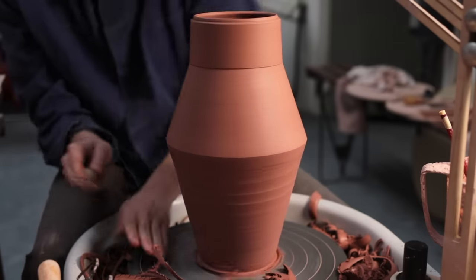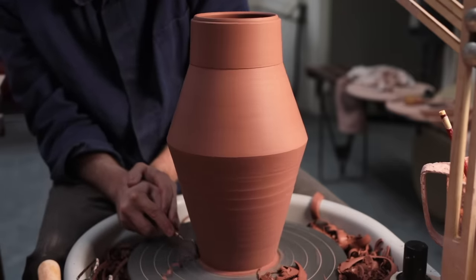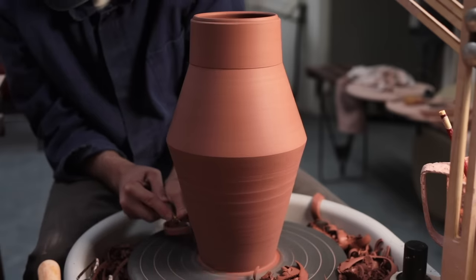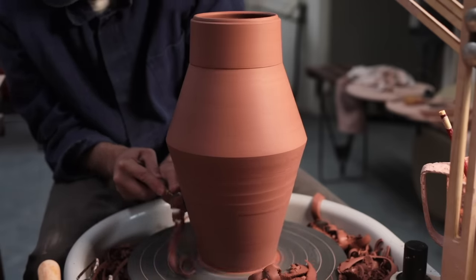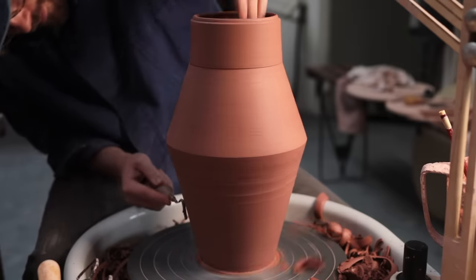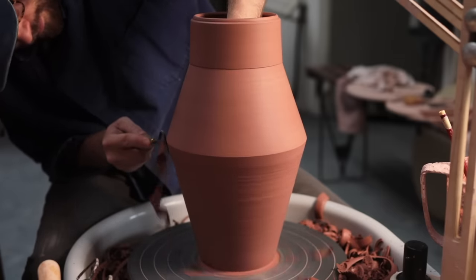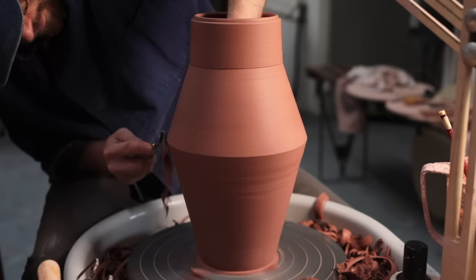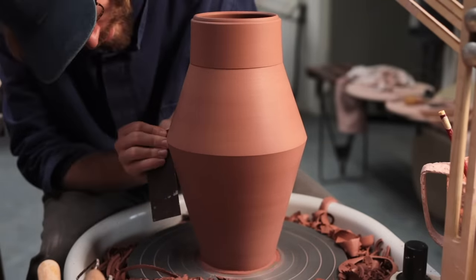I just inserted my left arm inside the pot to feel opposite the area I was turning. This way I can feel exactly how thick the walls are, as I need to be careful — if they're left too thick, the pot will feel bottom heavy, and if I trim them to be too thin, the weight of all the clay above can actually cause the walls to buckle and bulge outwards slightly around the base, which, as I'm trying to create such exact angular forms, never looks good.